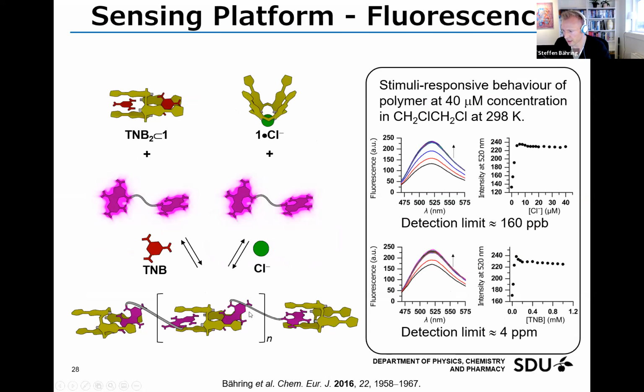So we made this supramolecular polymer, and we investigated the fluorescence increase upon introducing trinitrobenzene and also with the chloride anion. And you can see here with chloride, we haven't got complete quenching, and we're doing this experiment at 40 micromolar. So it also depends on the total concentration of this supramolecular polymer. But as soon as we add in anions, we can see a fluorescence increase of this system, which is interesting because rarely you have a fluorescence turn on when you detect anions or nitroaromatic explosives. Anions tend to quench fluorescence.